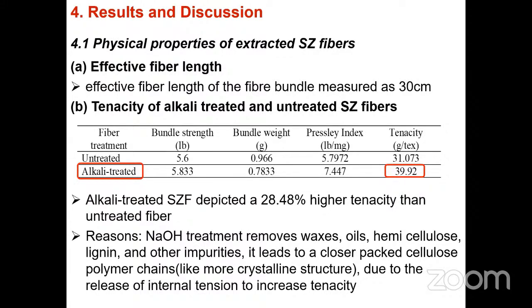According to the table, you can see 28% higher tenacity in alkali treated Sansevieria zeylanica fiber, because the sodium hydroxide removes waxes, oil, hemicellulose, lignin and other impurities, leading to closer packed cellulose polymer chains. Due to the release of internal tension, this increases the tenacity.